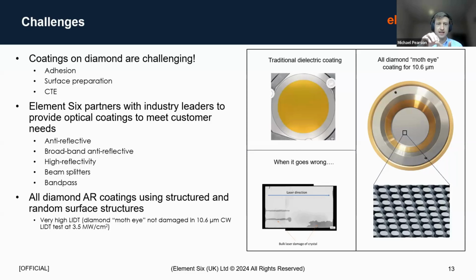Surface preparation, again, certain ways of cleaning the diamond can lead to surface modification, which can in turn lead to surface absorption. So we've got to be careful of that. And then diamond's very low coefficient of thermal expansion means that once you've got layers on top with different coefficients of thermal expansion, that system can be quite sensitive to increases in temperature, which are typically what you get when you have a small amount of absorption in a coating layer on an optic. So these things really make it quite a challenge.